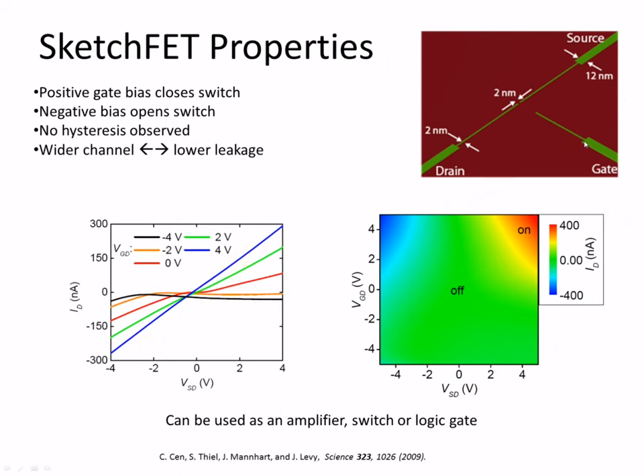The transistor basically works by applying a positive voltage to the gate, which then allows electrons to move through this channel. You see that when the gate is 4 volts, we have a straight line for the drain current as a function of the voltage between source and drain. So the current is limited not by the impedance of the channel, but rather by the leads themselves. When you lower the gate voltage, it becomes more and more resistive, and then eventually it turns off altogether. You can see that these curves don't all cross to 0, because there is some leakage current, which can be controlled by changing the distance between the gate.